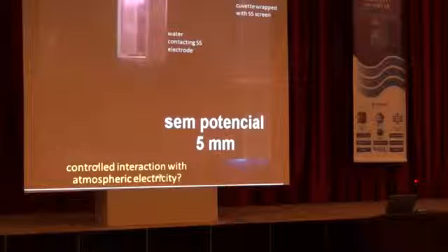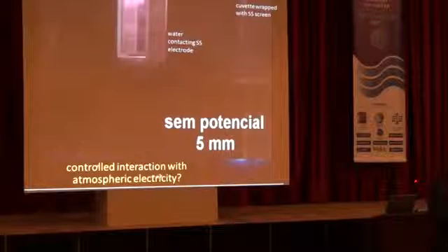But when you compare the changes in potential from different pixels, you see that there is no evidence of charge transfer by any surface mechanism. So in many cases, we can see a pixel with very positive potential. It decreases, is surrounded by others with negative potential, and we don't see the corresponding change in the neighbors.